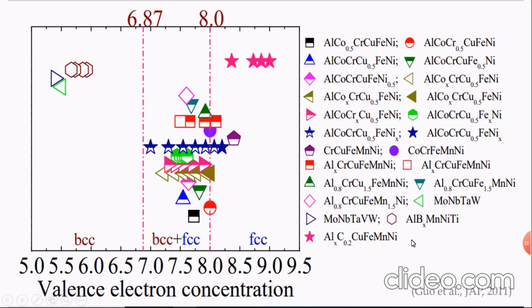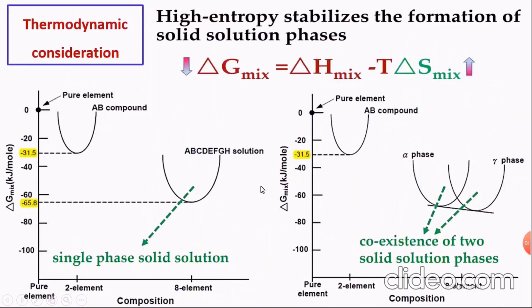Second thing to consider is the thermodynamic consideration of the system. Why? Because the main concept, as I said, is that high entropy stabilizes the formation of solid solution phases. To form a solid solution, we have to decrease the Gibbs free energy. As you study in thermodynamics in the bachelor degree, if we maximize the entropy, we will decrease the Gibbs free energy. At that time, we can obtain solid solution. Otherwise, we can obtain intermetallics.